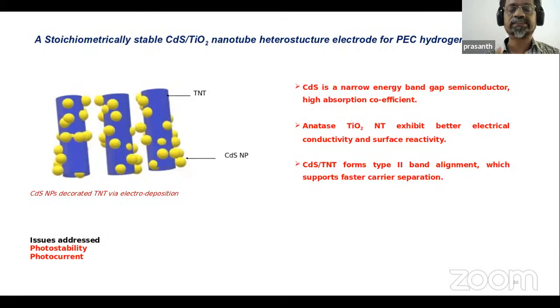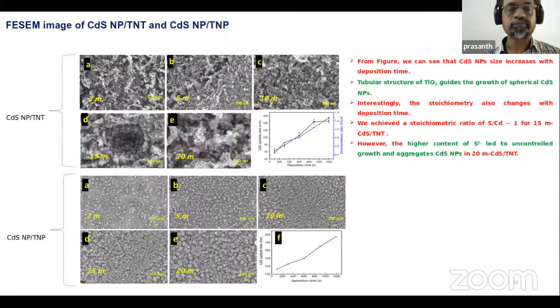Now, in this case, we used a CdS nanoparticle that can be nicely decorated with the TiO2 nanotubes. So CdS can absorb light from the visible region of the solar spectrum, where you have maximum photons available. So those photons can be harvested, and then electron hole pairs can be created. That electron can be transferred to the TiO2 nanotubes.